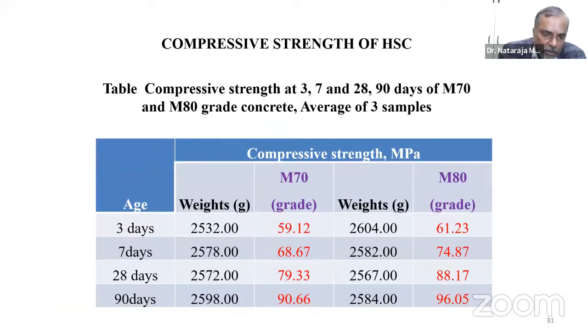And kindly see the compressive strength. It is quite appreciable at 3 days, 7 days, and 28 days. I have put it here. Kindly see. So 59, 68, 79, and 90, as far as M70 concrete is concerned. At 28 days, I'm getting 79. What I'm expecting to get is just 70 plus t times s, the standard deviation times the statistical value, that extra component to take the difference from lab to the field. That is where about 6 MPa of extra I'm expecting. 76, probably I would have been happy, but it is slightly more than 76. I'm getting about 79, rather close to what I wanted. So I'm not doing any further change.